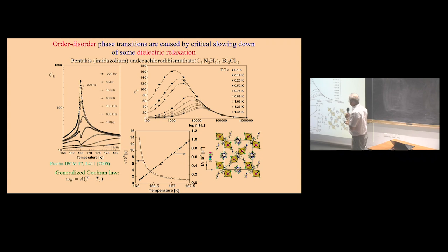And this is due to dielectric relaxation describing, let's say, in this organic system, you have vibration or hopping of a big part of molecules among more potential minima, and this is somewhere in kilohertz range, and this hopping is slower and slower if you are approaching phase transition.